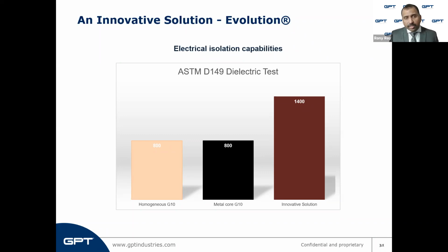Evolution, on the other hand, with its new coating, has a minimum dielectric value according to ASTM D149 dielectric testing requirements of 1400 volts per mil. And that is the minimum rating. It has gone up to 1800 volts per mil in some of our tests.